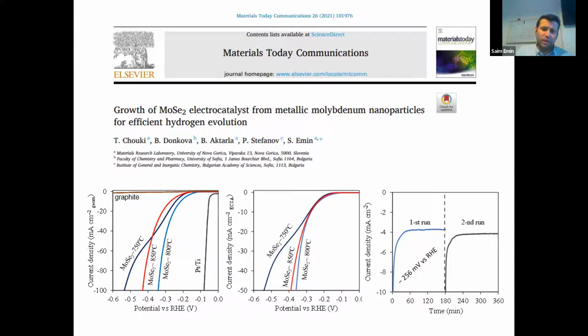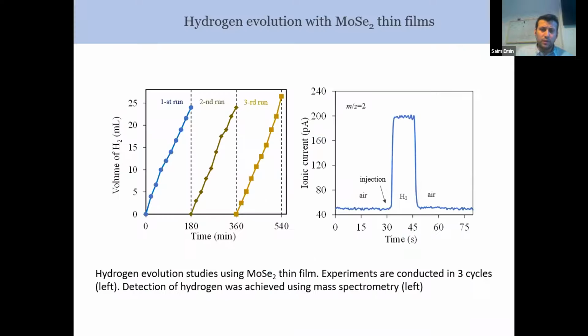On the very right side is again the stability plot. Initially the current drops, but later with time it stabilizes. And after stopping and running the experiment again, it's repeatable. So there is some kind of charging on the graphite surface. However, the fact that this current is stable after, let's say, 60 minutes in the first experiment, and in the second after 240 minutes, shows that the films are stable.